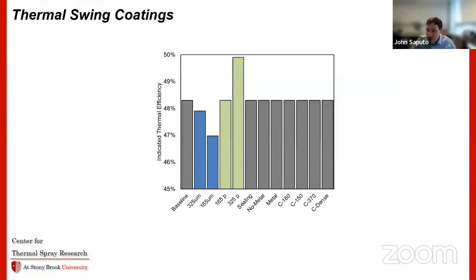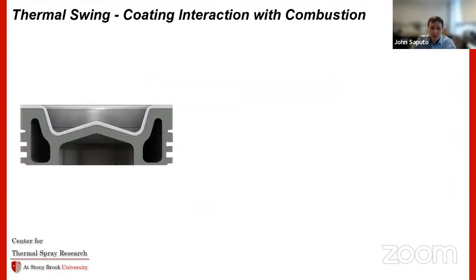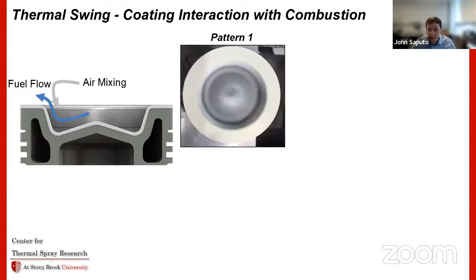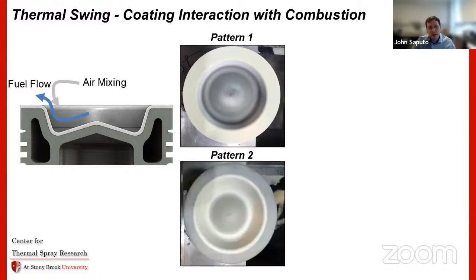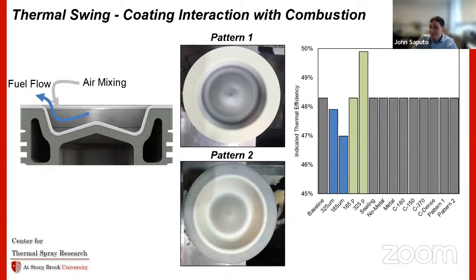So our thought process went to something like, hey, maybe the coatings actually influence combustion in some other way. Normally you have this complex bowl geometry, with fuel flowing and air mixing into the system at the same time, and maybe there are some other interactions that we're not thinking about happening in this system. So we decided to make pattern coatings. You can coat only the outer edge of the piston, where there's little air-fuel mixing and little interaction with the combustion process, and then do the exact opposite and coat the inner portion. But when you do this, something miraculous happens. Absolutely nothing.